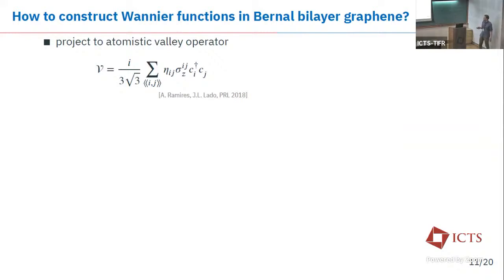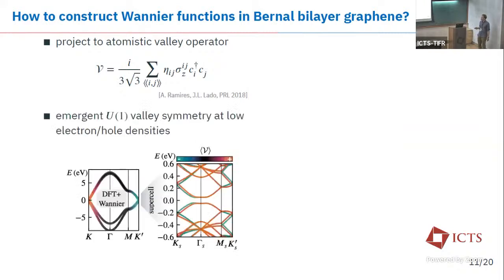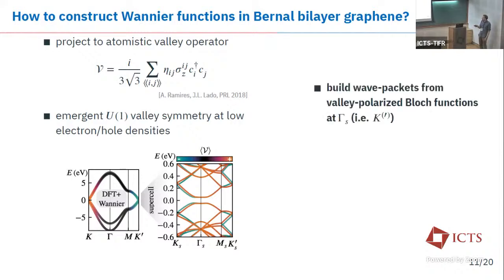So we go ahead and first, before writing down the Wannier functions, try to use the valley symmetry of the model. We do this by projecting the band structure onto the atomistic valley operator that you can read up on in, for example, this reference. This quantifies that there is an emergent U(1) valley symmetry at low electron-hole density. I was talking about this before, but we actually do the calculation and see that the expectation value of the valley operator is very close to 1 in the energy window that we want to do the Wannierization for. Then we go to the supercell point at gamma, which corresponds to the original K and K prime points.